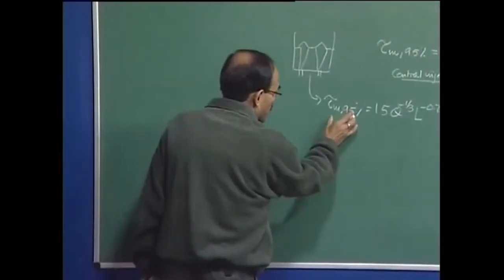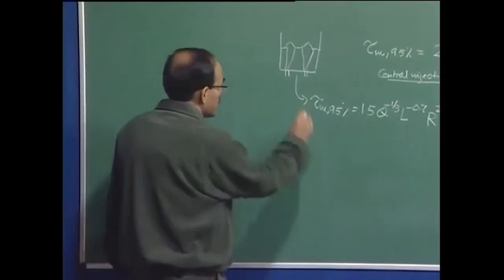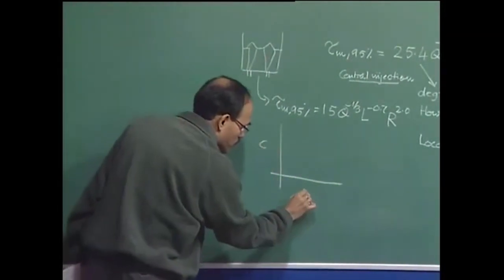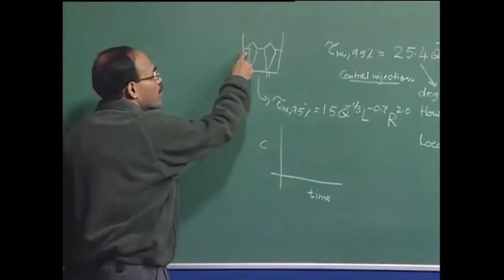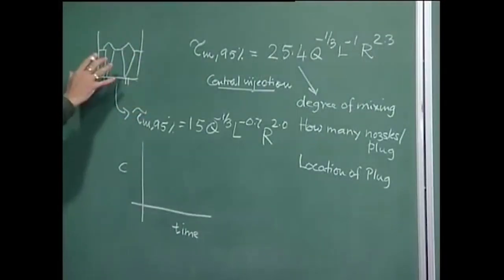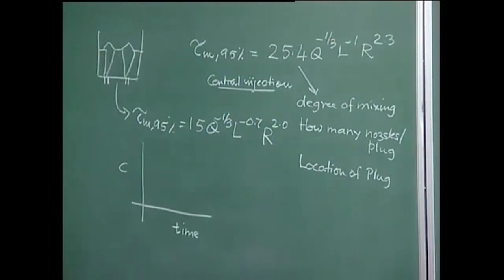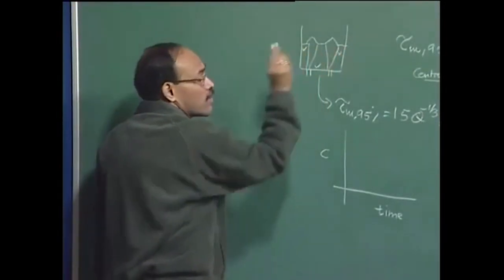Let me explore a little bit about mixing time. Suppose when you add a species into the system and monitor a concentration — concentration versus time at the monitoring location, which could be anywhere in the system. We talk about the reactor mixing time, which is important because if mixing time depends on position, since at various locations the intensity of fluid flow and turbulence are not identical, the rate of mixing will vary from one location to another.